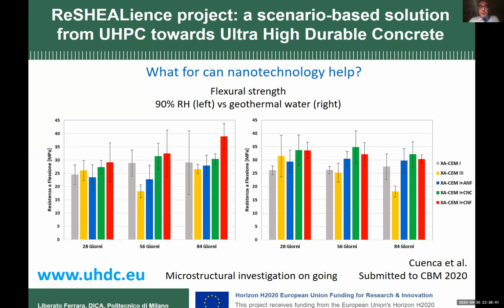When we characterize our material, we cure it in ideal conditions. But if we build a structure to serve as a basin for geothermal water, we cannot wait 28, 56 or whatever days for curing in ideal conditions. The basin shall be used immediately, so it will cure under the aggressive water.